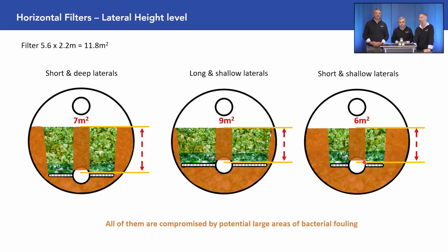The worst case scenario is if your laterals are very high up in the filter and very short. That really can't achieve much filtration performance after the first few backwashes, because this surface area is really only the active surface area that you'll be using. This is roughly half of what you expect, right? Yeah, roughly half of what you think you have, and because of that, you are designing for a flow rate of 11.8 square meters, but you're only using 6 square meters. So your filtration velocities are ridiculously high. Yeah, and that's also impacting our AFM. Also, that performs much better than sand, but it will impact the AFM. You're not anymore on the 10 that we discussed, or the 20. Exactly. You're double.